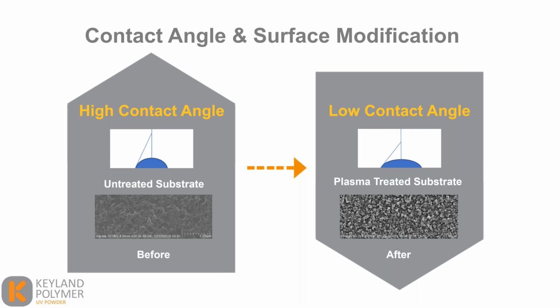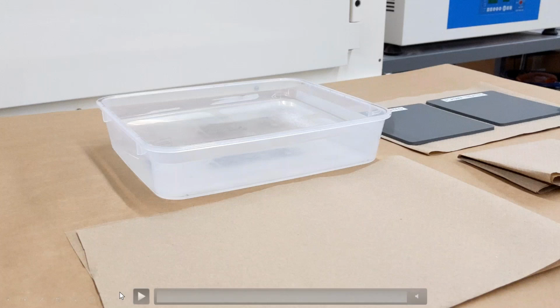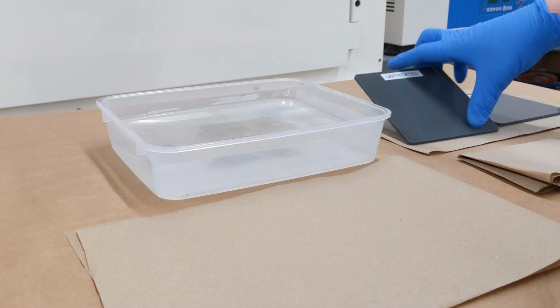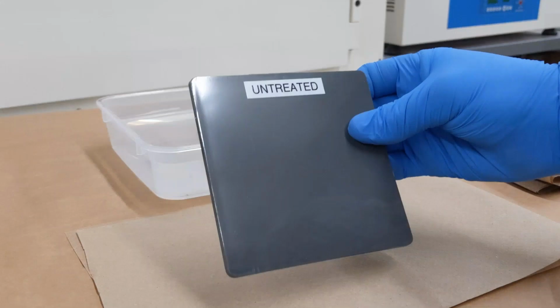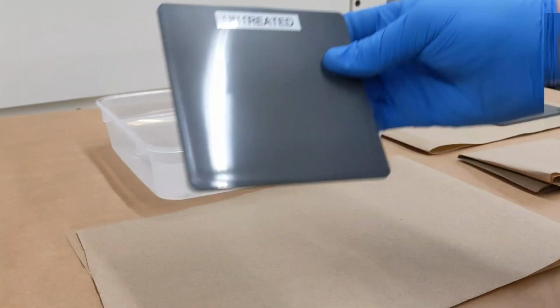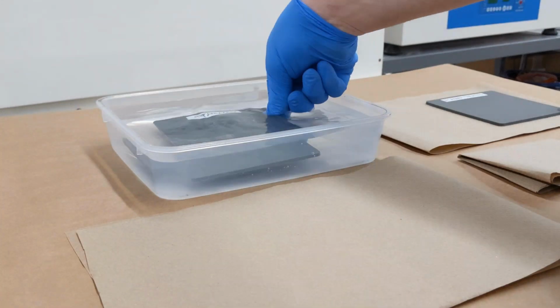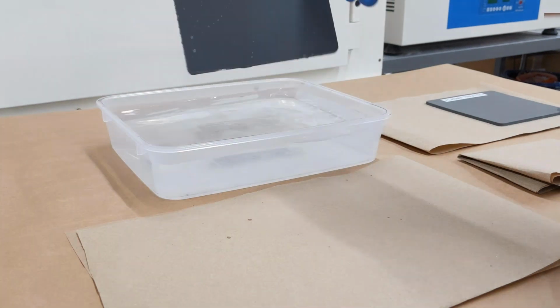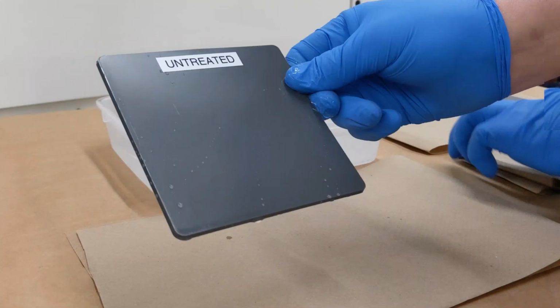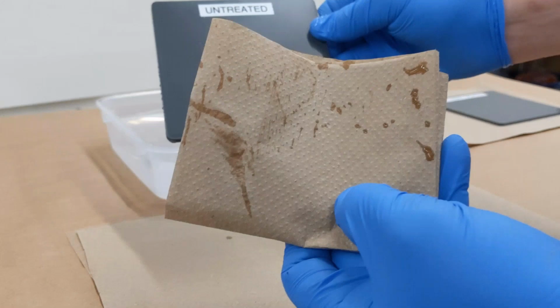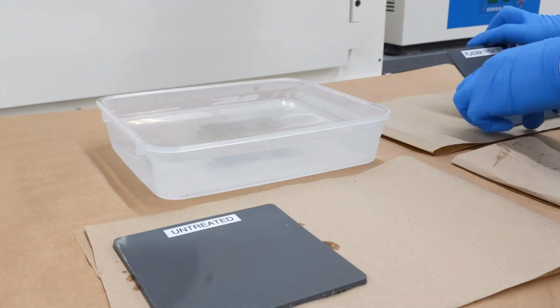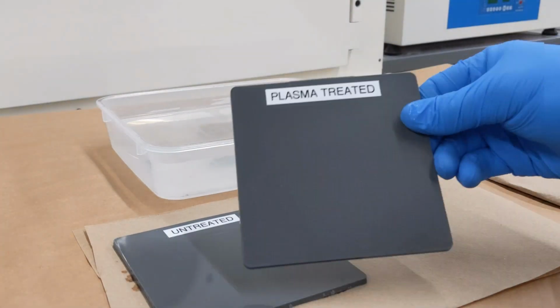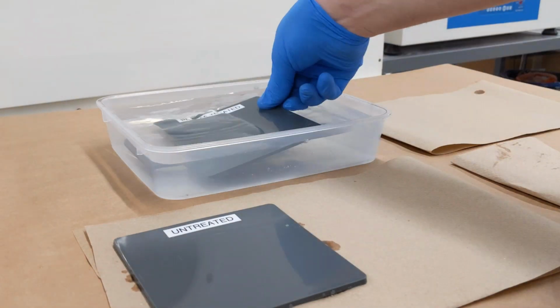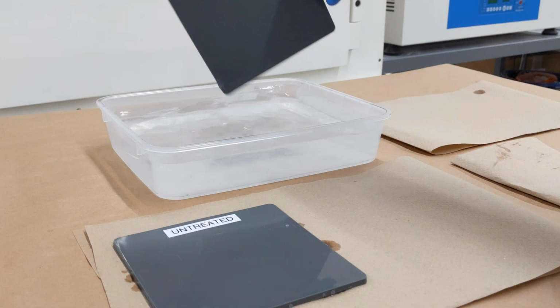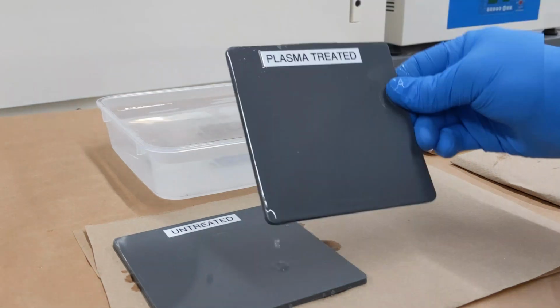So to help visualize this, we put together a simple video. And what you're seeing here are two plastic substrates. One is untreated and the other is treated with plasma. And we're going to dip them into the water. And you'll see what this does. Immediately the water runs off. There's not much water staying on the substrate. However, after treating, we improve wettability drastically. And you'll see in just a moment here how the surface energy profile changes to improve wettability.